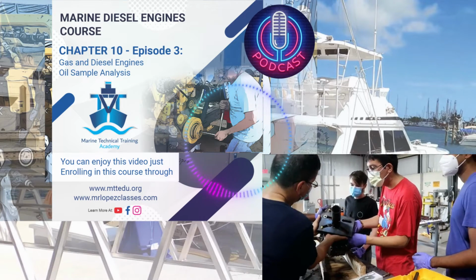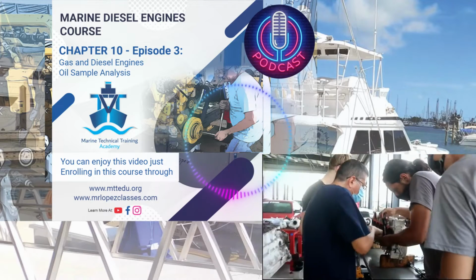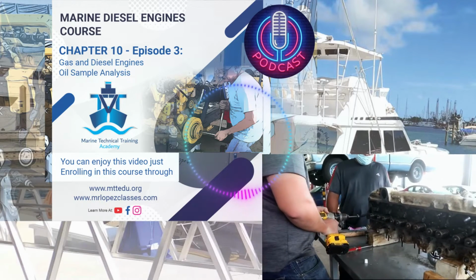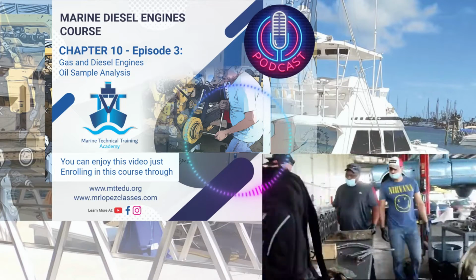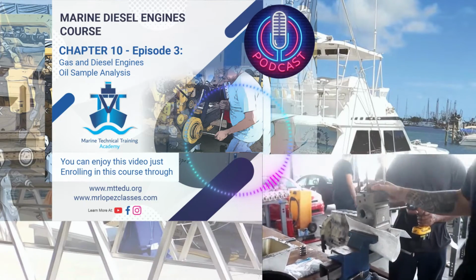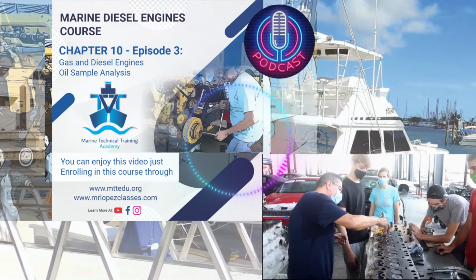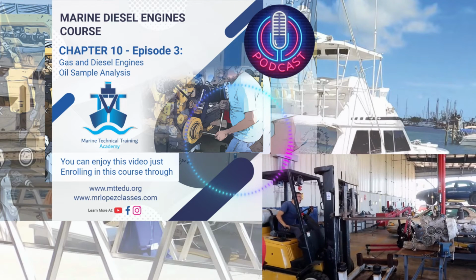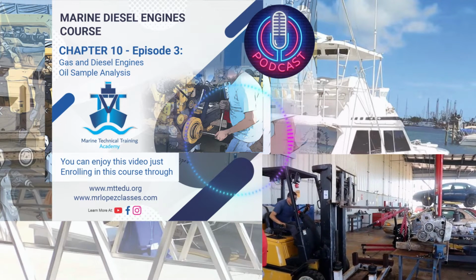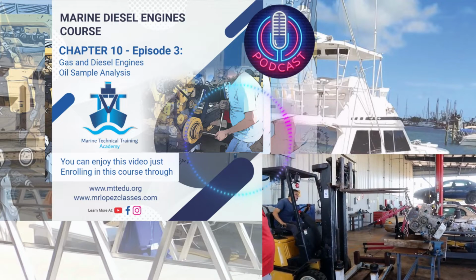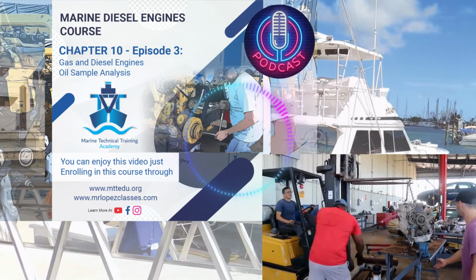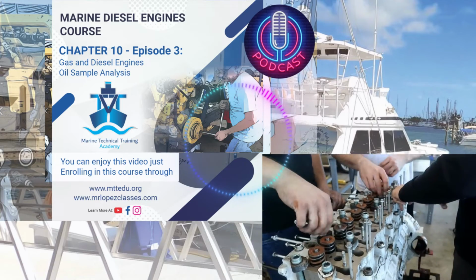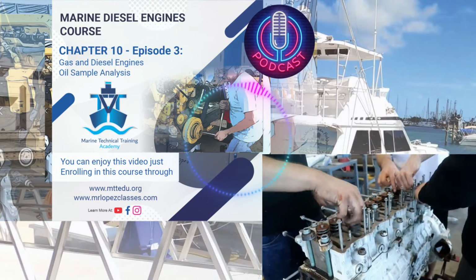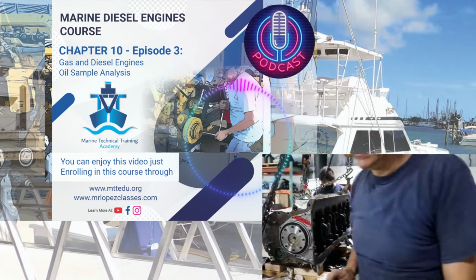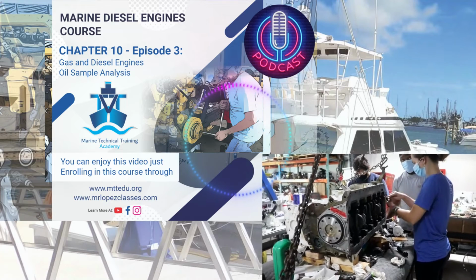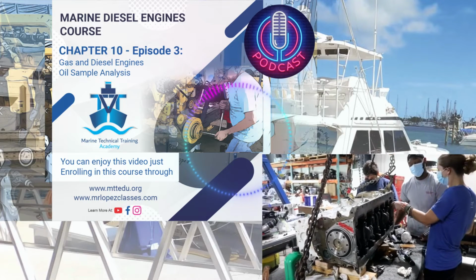Another important element is copper. The concentration should normally be between 10 and 50 parts per million. Where do we find that copper? Okay, on the bearings on the turbo. You remember those bearings, and the bearings on the small end of the connecting rods. That small end is also copper. It's a bronze alloy. Yes, in general it's in plain bearings. And what is the consequence? Immediately, if you have problems on the turbo, you have black smoke, you have noise, and of course, in some cases, low oil pressure. And what is the solution? Rebuild the turbocharger in that specific case.